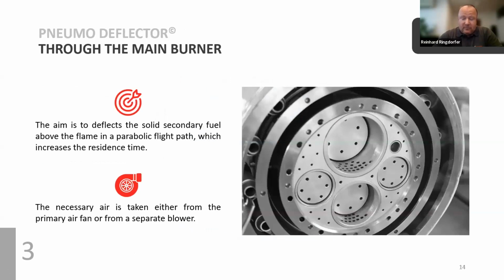As I said before, shortly after our focus on the rotary kiln process, the cement industry, we delivered the first burners with secondary fuel firing capabilities, so with a simple pipe through the main burner. And since then, we were looking for solutions to increase the amount that can be fired through the main burner by somehow influencing the particle when it leaves the burner. The latest device invention we are using is the pneumodeflector, which has been around for the last 10 years. The goal is basically to deflect the particles above the kiln burner axis to alter the flight path and to extend the residence time, the flying time, and therefore the combustion time.